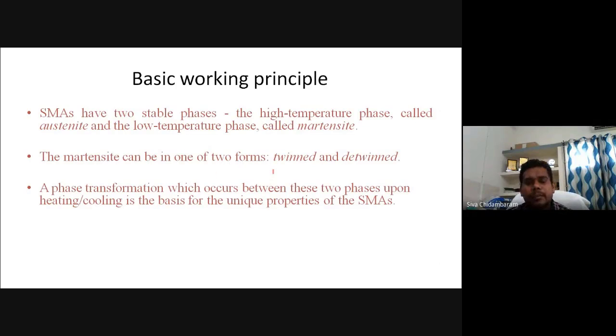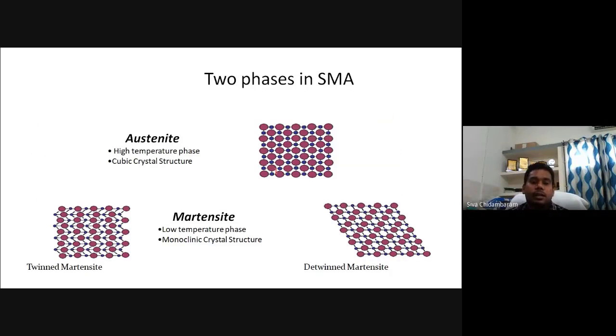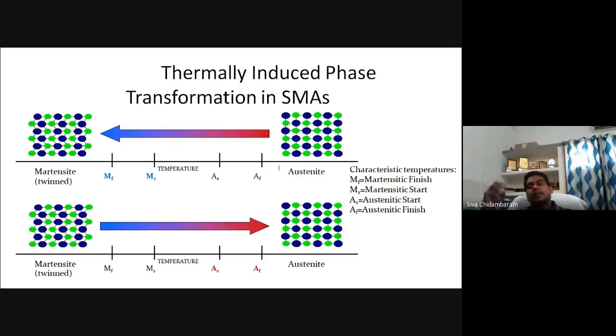The reason for this is that there are two phases in this material. One is austenite, another one is martensite. When it is in the high temperature phase, it becomes austenite, and when it comes to a low temperature phase, martensite happens. So this is how the internal atomic crystal structures are deformed to bring you the real shape and to have the memory effect.